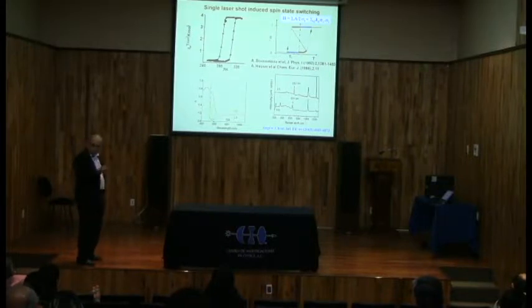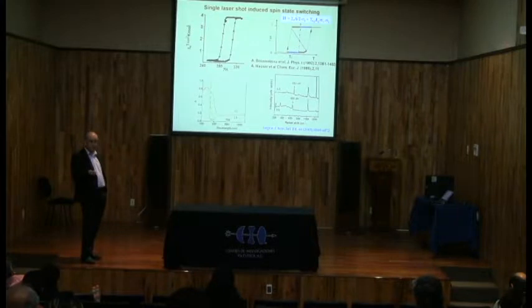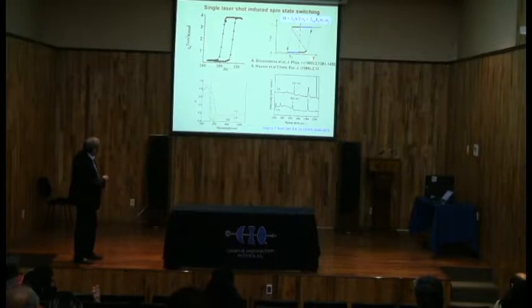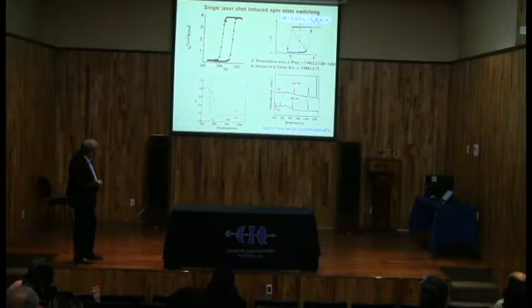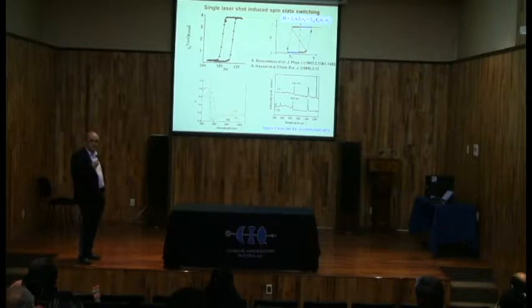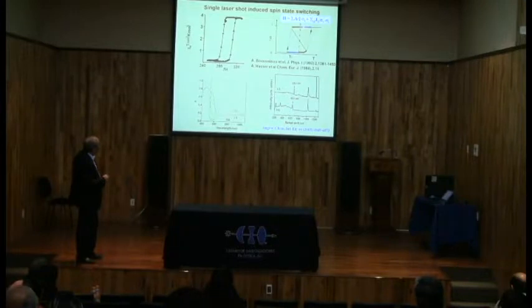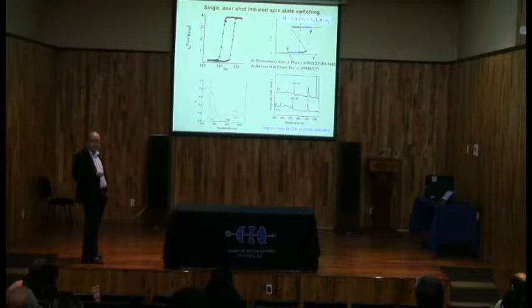Okay, this is how we can send our energy. And then, of course, if you send this energy and you want to see if you have effectively switched your system, you need to measure it. If you look at the Raman spectroscopy of this system, you see that from low spin to high spin, you have a Raman shift of more than 30 wave numbers. That means that in principle, you can switch your system from low spin to high spin reversibly by sending green light, and by measuring the Raman spectroscopy, you expect to follow the switching.